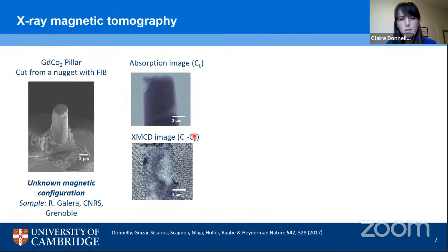But when we take the difference between the two circular polarizations, we see quite clear bright and dark patches within the magnetic pillar. Now these correspond to the magnetization pointing in and out of the plane. And it tells us a couple of things. First of all, our sample is magnetic, which is great. Secondly, we seem to have quite a complicated internal magnetic configuration. However, with this single projection, we can't really see what exactly is going on.